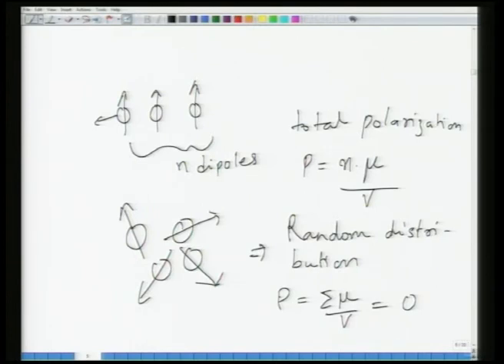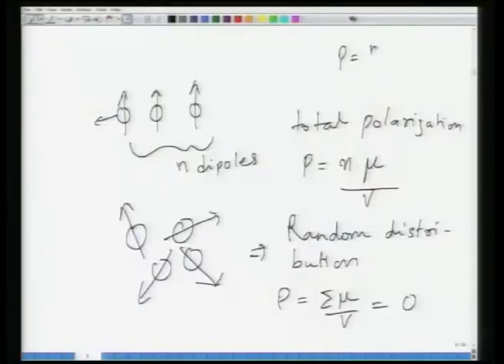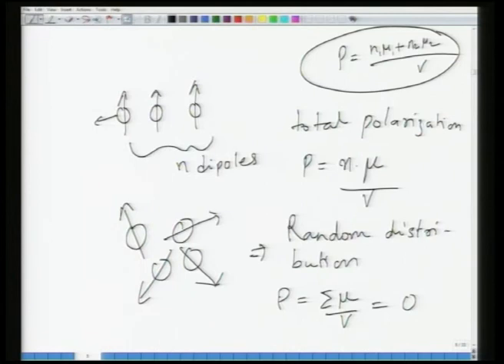Then we looked at, and of course before we go further, we can say very clearly, when you have dipoles aligned in one direction, in that case polarization is nothing but the sum of all the dipoles, or dipole moment multiplied by the number of dipoles over the whole volume. And if the dipole strength was different, then it would be P is equal to N1 mu 1 plus N2 mu 2 etc., divided by the whole volume. So this would be the case if the dipole strengths were different in different parts of the crystal. But if you have a random distribution of dipoles, then polarization is likely to be equal to 0.